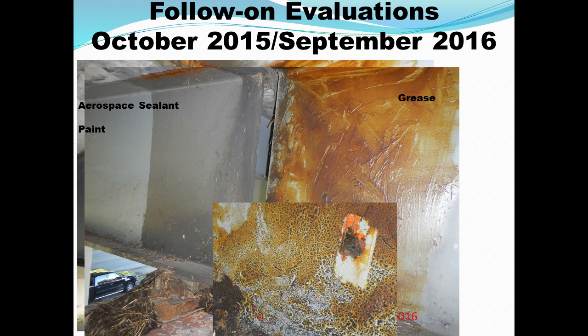This is one where just a few months back I had the guys go out and scrape off the spot that had the rust originally, one of the spots. And that area, I mean, it's still got some rust underneath it, but it hadn't grown. It's just sitting there sealed with the grease. The grease is ugly. It picks up, as you can see in the inset, a lot of debris. It's ugly, but it seems to be doing a pretty good job, a pretty low-tech approach.